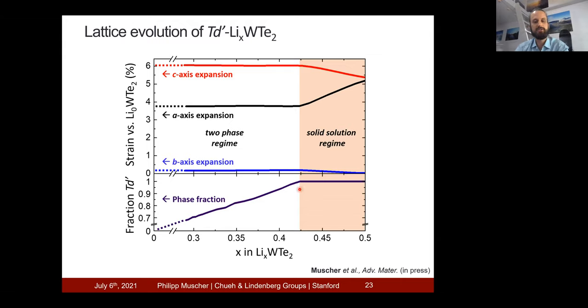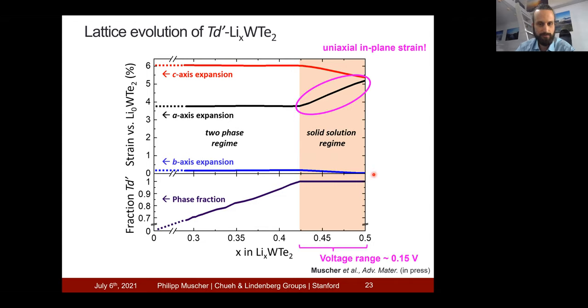And in this solid solution regime, we actually see dramatic changes to the lattice parameters, especially the in-plane A-axis lattice parameter, which is changing by 1.4%, while the other in-plane direction, the B-axis, is almost not changing at all. So this means we have a uniaxial in-plane strain. And I want to guide your attention to how little lithium insertion is actually needed to drive this 1.4% in-plane strain. And also the voltage range that we have to apply in our electrochemical system is only 150 millivolt to achieve this.